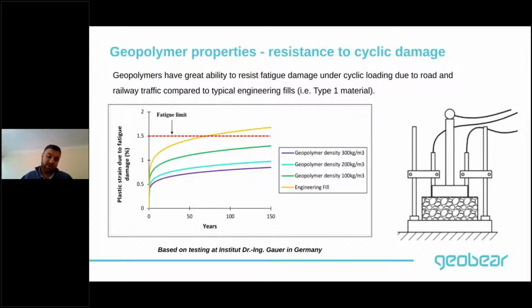If you compare, for example, the geopolymer fatigue performance to typical engineering fills like a Type-1 material, geopolymers can last up to 120, 140 years under fatigue loading. But Type-1 material, for example, the best Type-1 material that you can ever source probably will last you around 70 years. So it's quite superior from that point of view.